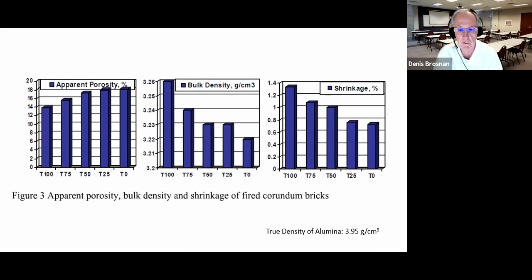And there's a lot of data here. You can look at the apparent porosity. They say the 100% tab alumina composition was about 16% porosity. The bulk density was up here about 3.26. Well, the true density of alumina is about 3.95, although the tab wasn't quite that dense. So you can see that there, if you do a little bit of Sherlock Holmes investigation, there probably were some closed pores as well as open pores. So this apparent porosity represents the open pores.